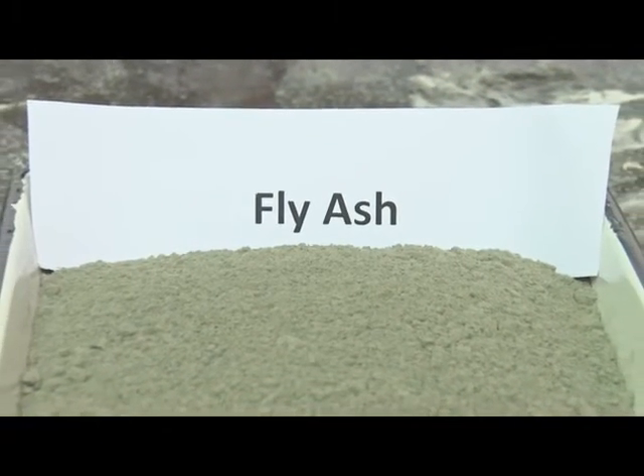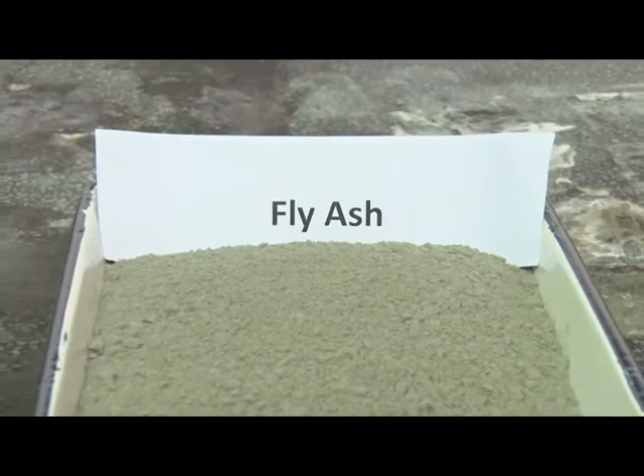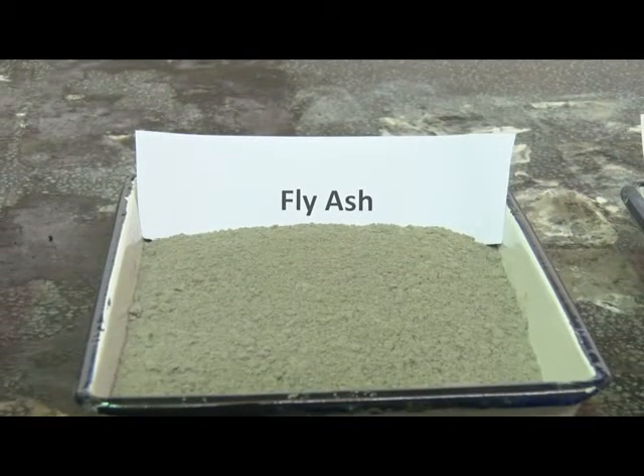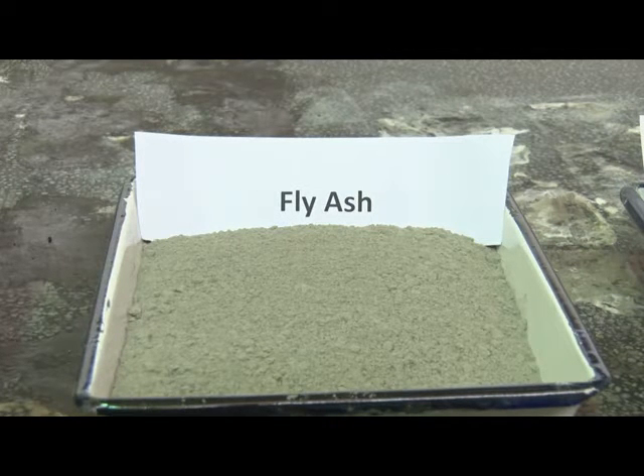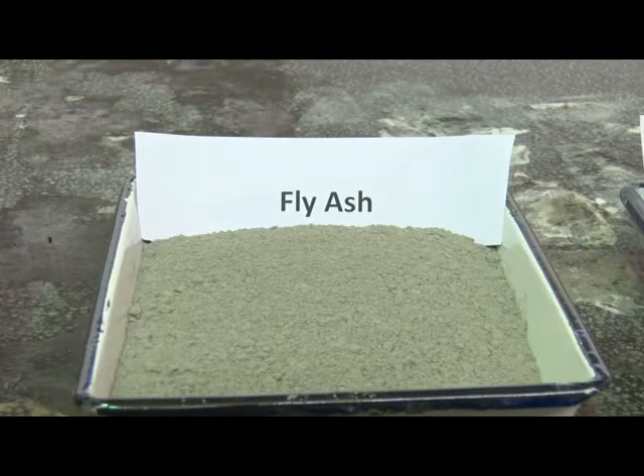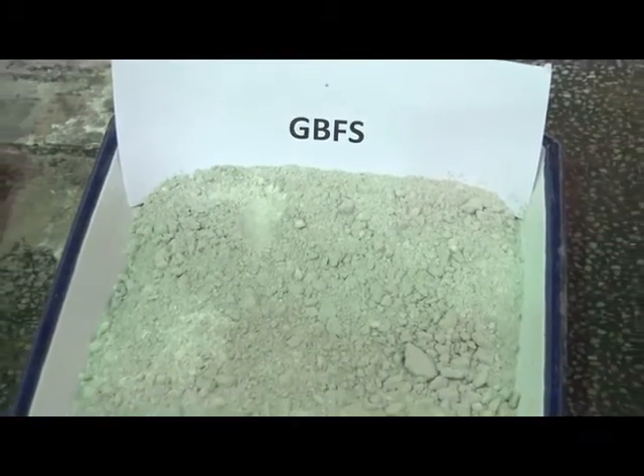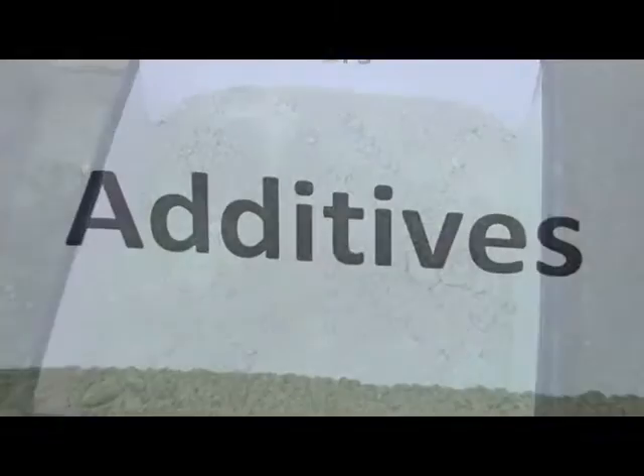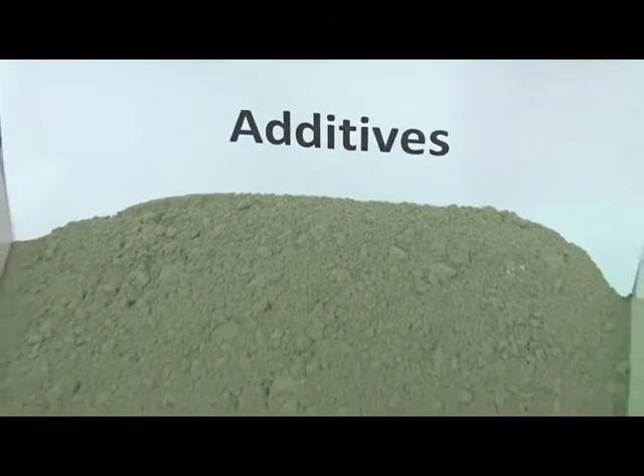Though any aluminosilicate is suitable, CSIR NML has focused on geopolymers based on industrial by-products. Fly ash is used as the primary starting material. Ground granulated blast furnace slag is added to enhance the reaction rate, and some additives are used to achieve the desired chemistry and properties.